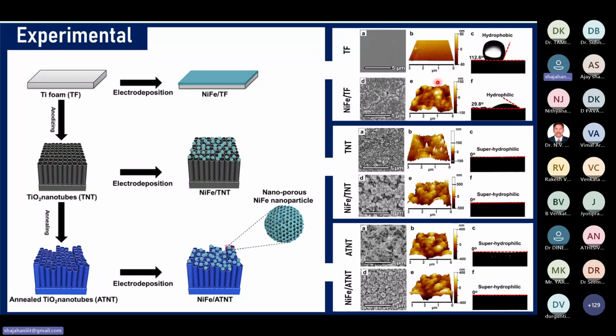Initially it is hydrophobic, as we found in the wettability test. After anodizing, we got superhydrophilic. After that, we did annealing. So we got annealed titanium oxide nanotubes. That is also superhydrophilic in nature. Why did we do annealing, when it is already superhydrophilic after anodizing? Because it is amorphous.